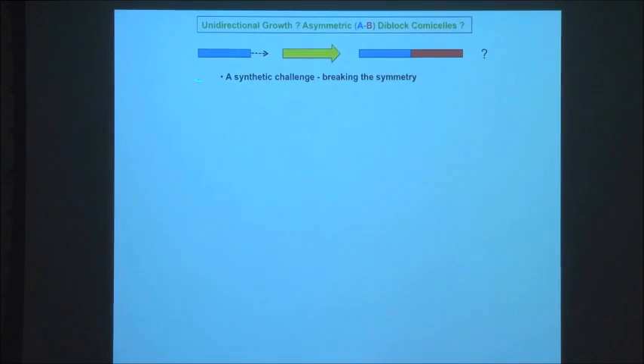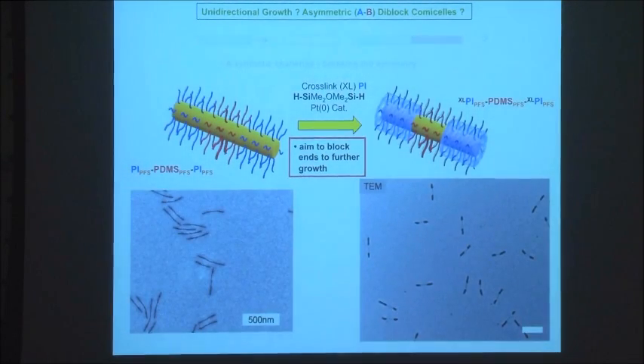So what we want to do is make micelles where we can use crystallization-driven self-assembly and just grow in one direction. This will allow us, for example, to make AB block structures, which might be interesting, or ABC. And in fact, if you make one end hydrophobic, the other end hydrophilic, you might be able to self-assemble these into new types of structures, super micelles, which would be further up the length scale from normal micelles. So how do we do this? I'll share with you one method that we published last year.